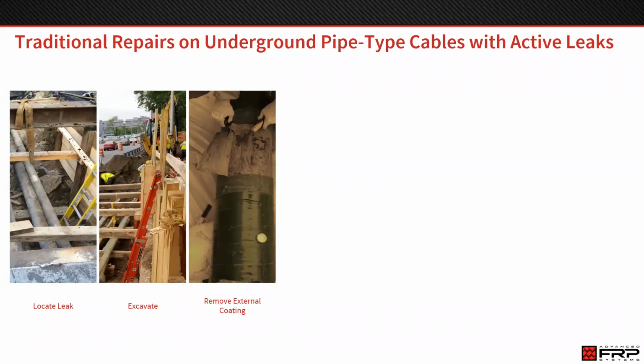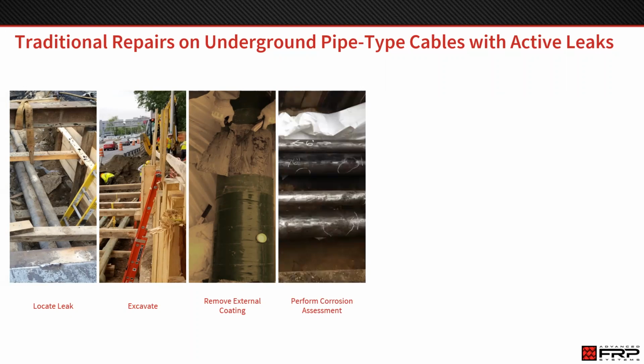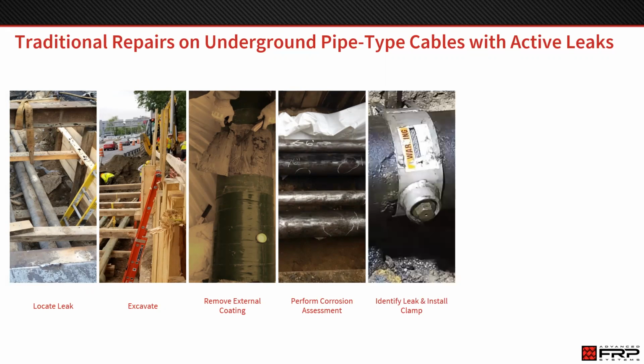Prior to doing any sort of repairs, you're going to have to remove the external corrosion barrier, a coating or a tape coat or whatever it might be. If you want to repair more than just the exact spot of the leak, you can do a corrosion assessment and see where else on that area you've unearthed may be experiencing corrosion. A clamp can be installed to stop the active leak from leaking.